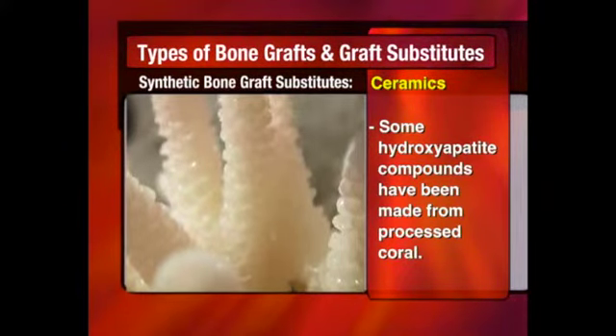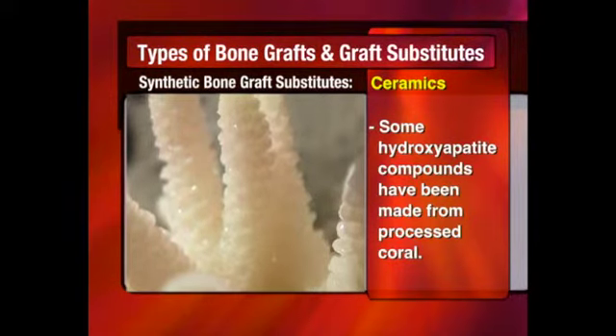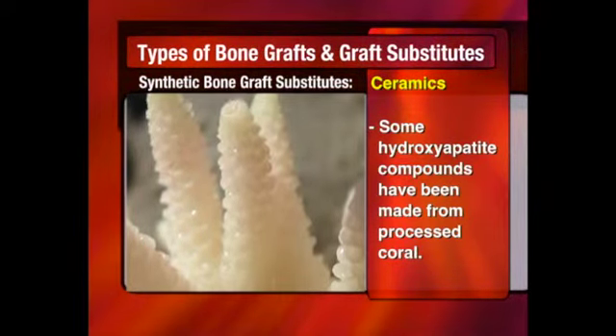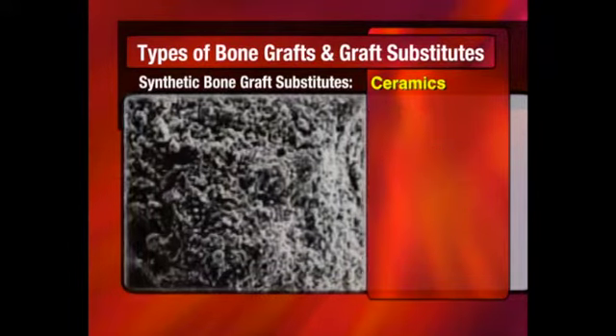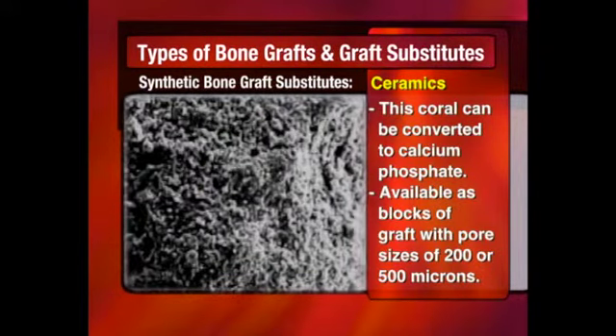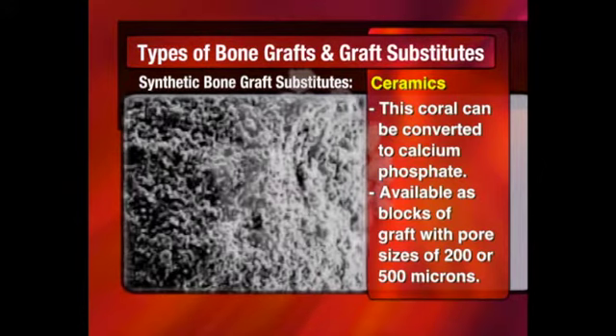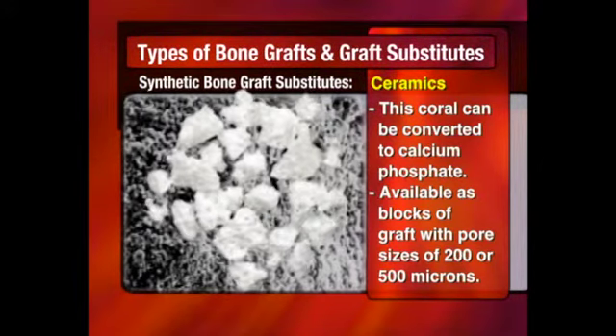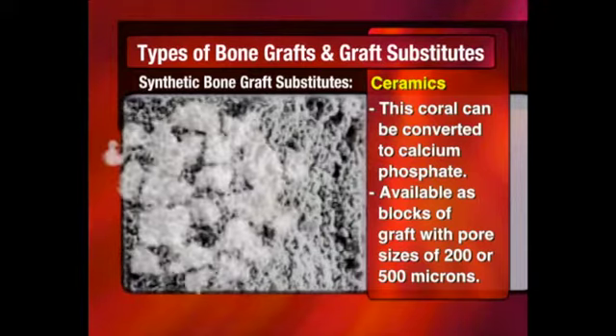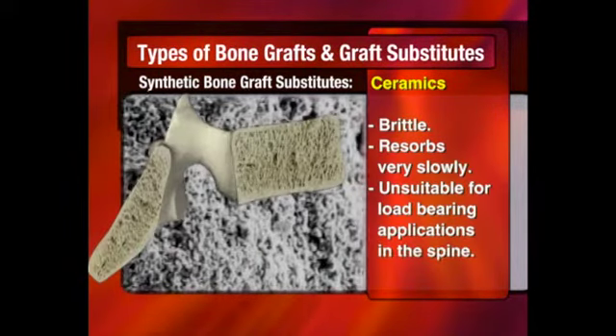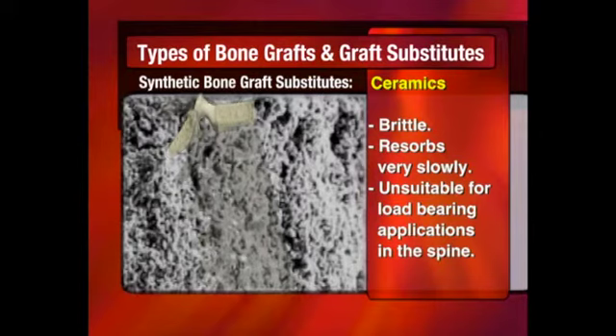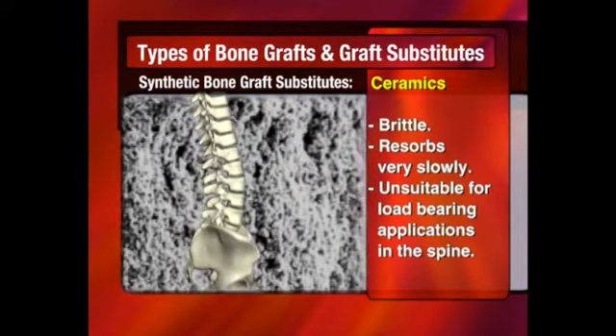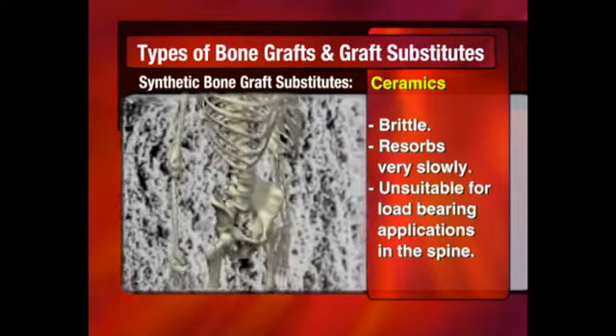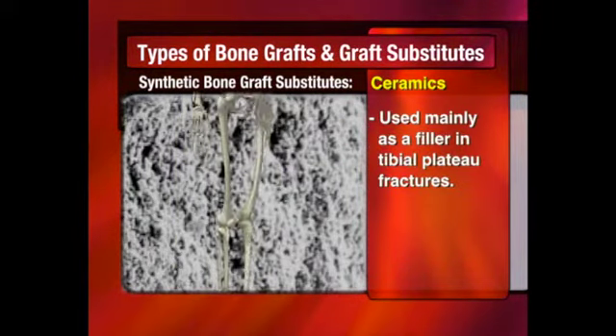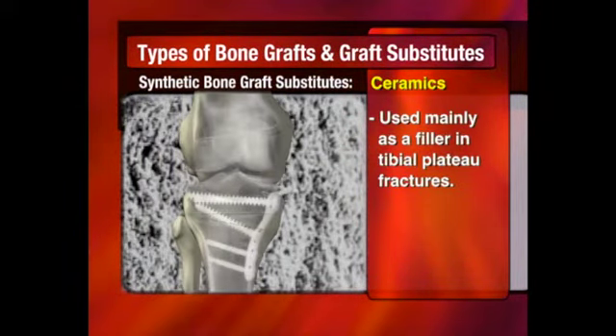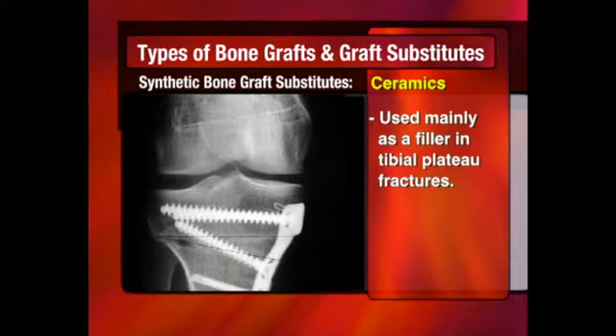Some hydroxyapatite compounds have been synthesized or made from processed coral. Specific species of sea coral contain a calcium carbonate exoskeleton closely resembling the microstructure of bone. This material can be chemically converted to calcium phosphate and is commercially available as blocks of graft with pore sizes of 200 or 500 microns. Although this material has high compressive strength, it is brittle and resorbs very slowly, making it unsuitable for load-bearing applications in the spine. Its main application has been in tibial plateau fractures, where it serves as a filler material.